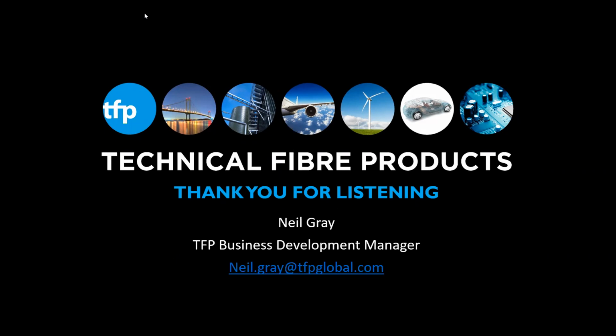Yes, they are. We have ongoing commercial use of the veils with epoxies, with polyesters, vinyl esters, polyurethanes, prepregs. We have some specific veils that we've developed for use with phenolics, where the acid catalysts can be a bit of a challenge, but we've tuned the performance of the veils for those applications. We have ongoing commercial business in pultrusion, RTM, filament winding, vacuum infusion, and having the ability to tune the veils ourselves, both in R&D on a pilot line and in production, we can modify the veils to really optimize them for the specific application. But they are used either in development or commercially, really across all resin systems and all manufacturing techniques.